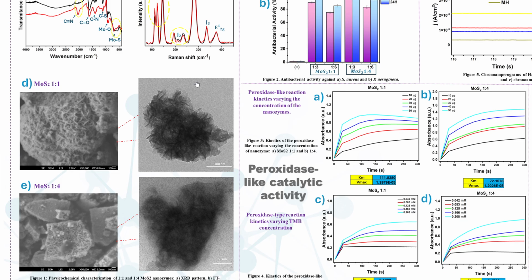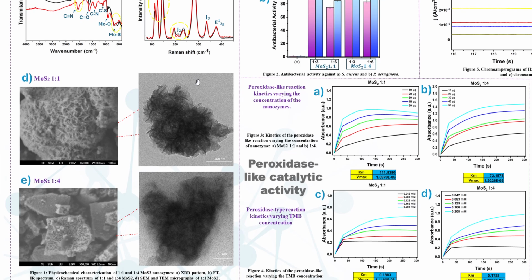The microscopy images also demonstrate that changing the molybdenum to sulfur ratio significantly modifies the morphology and organization of the resulting nanostructures. These structural differences are particularly important because the catalytic properties of molybdenum disulfide are strongly influenced by the edge, defects, and accessible active sites.